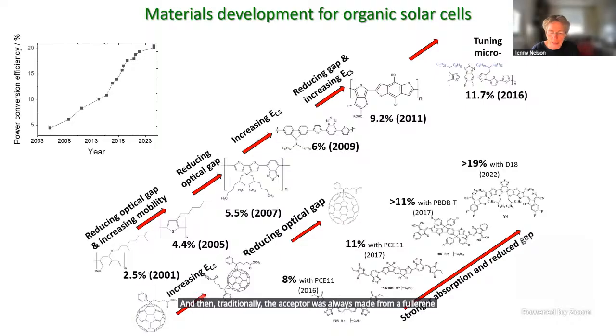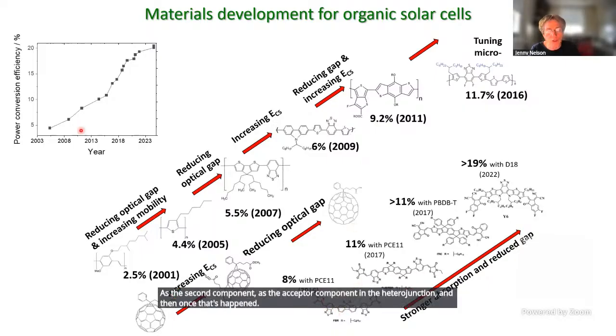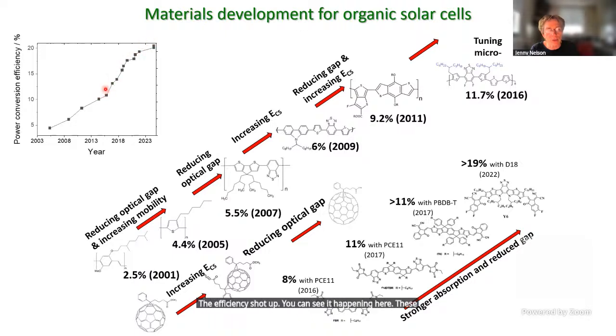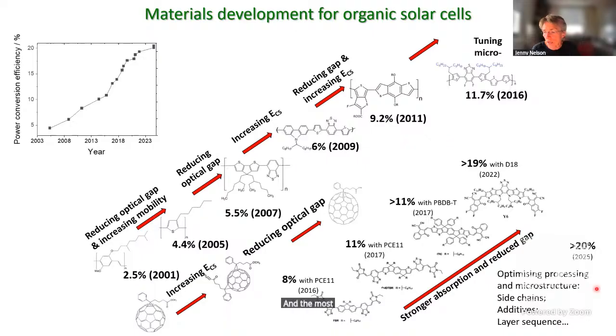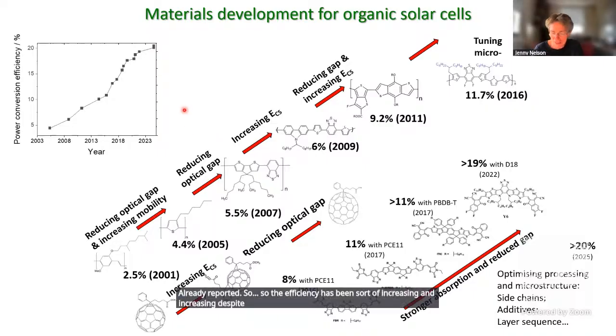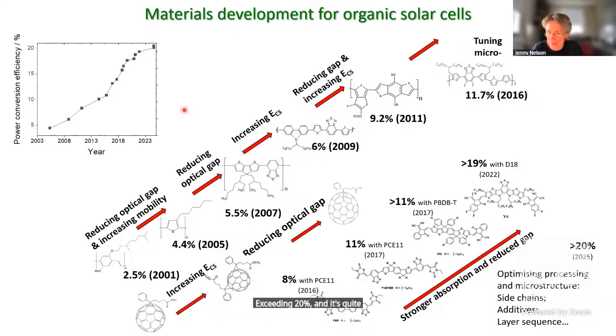And then about 5 or 6 years ago, a breakthrough was made where alternatives to fullerenes were found that were able to work well as the second component, as the acceptor component in the heterojunction. And then once that happened, the efficiency shot up. You can see it happening here. These are the new acceptors, and the most recent results are more than 20%. In fact, I have seen a 21% already reported. So the efficiency has been increasing and increasing despite expectations. I certainly didn't expect to be exceeding 20%, and it's quite exciting to see this happen.